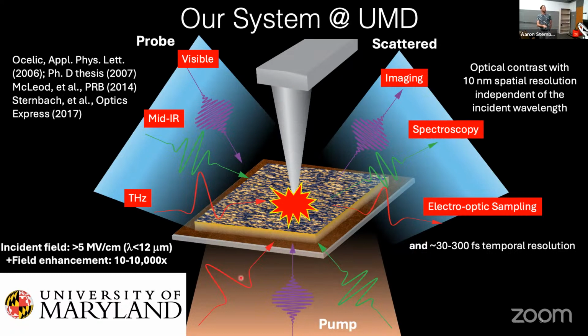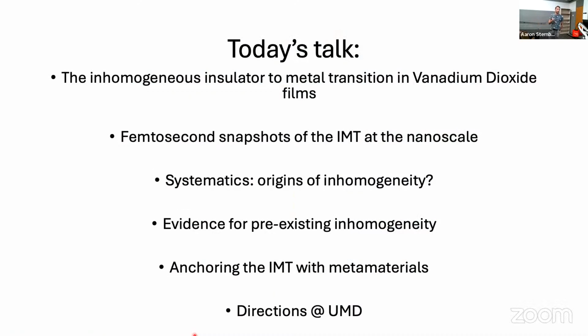Well, the system we chose, and which is here at UMD, has pretty high field strengths, so we can get field strengths in excess of about 5 megavolts per centimeter in free space at all wavelengths up to about 12 microns. The tip gives you an additional boost, which is known as field enhancement. So the fields are enhanced by a factor which is thought to be really large. So at terahertz frequencies, this factor is thought to get up to, say, 10,000. Although this is not something that's measured, this is something that's inferred from finite element simulations, but this is something we're interested in exploring. And so in today's talk, I'll be giving an overview of one system which this kind of measurements can be used for.